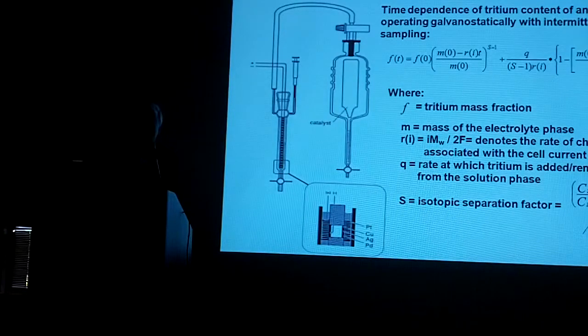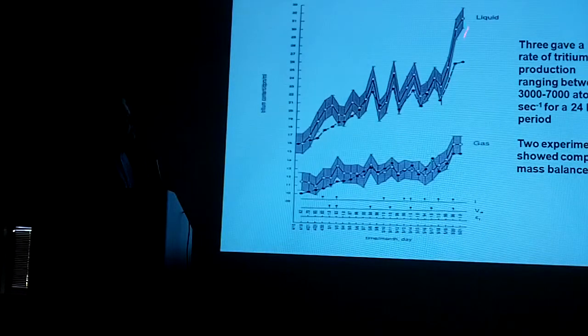Another thing that we did, there were reports that people were seeing tritium, and so we designed a cell co-deposition where we could collect both the gas and also look at the electrode and the solution, and again, a good electrochemist took care of all of the equations. Next slide. And when they did that, we saw that of the 5 experiments, 3 of them gave a tritium rate of production of between 3,000 and 7,000 atoms per second over a 24-hour period. Now, we know they didn't occur in a uniform process. We would see spikes occur, but when we averaged it over 24 hours, 3,000 to 7,000 atoms per second were being produced. 2 experiments showed complete mass balance, so 2 of those did not produce tritium.